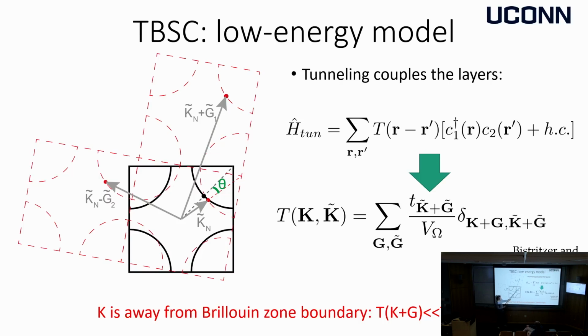And what happens if you want to consider the actual problem is that you tunnel between the two layers at momenta which are overlapping in this figure. So that means that for this point, for example, I need to take into account the first Brillouin zone. In the second Brillouin zone, it will overlap with a somewhat different point in the other layer, and so on and so forth. And in twisted bilayer graphene, this is very crucial because the Dirac points are at the corner of the Brillouin zone, so there are many, many processes like this, and the problem becomes complicated.